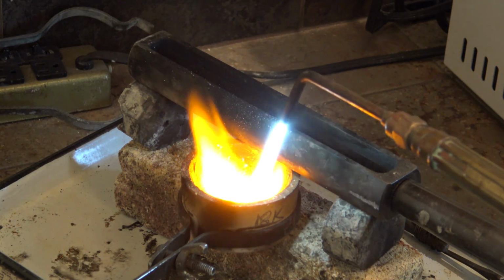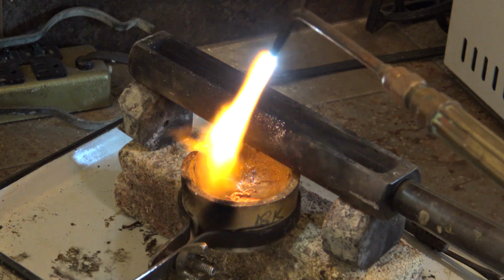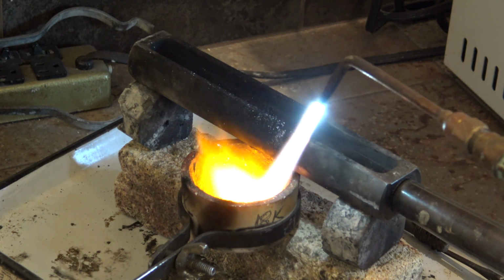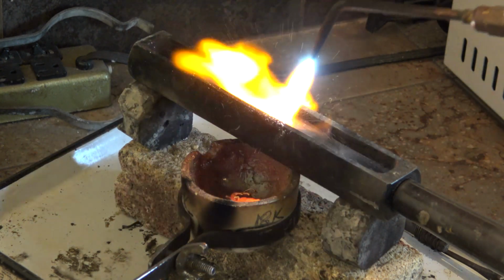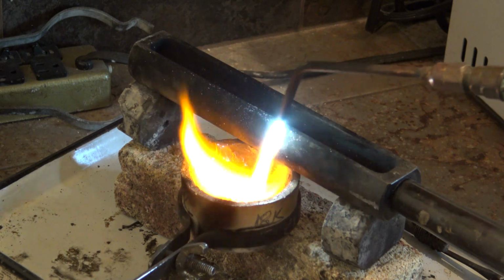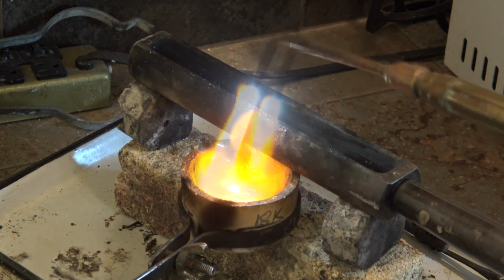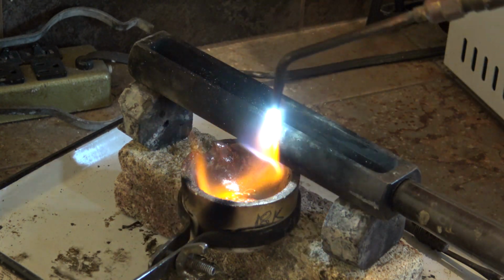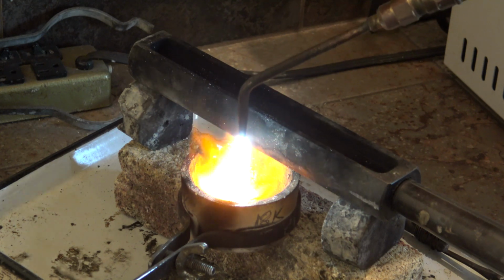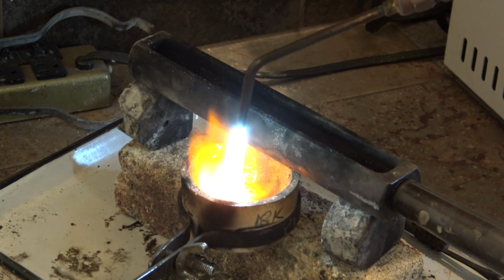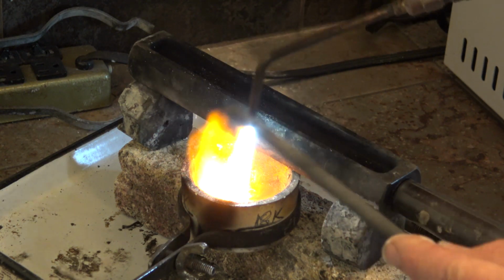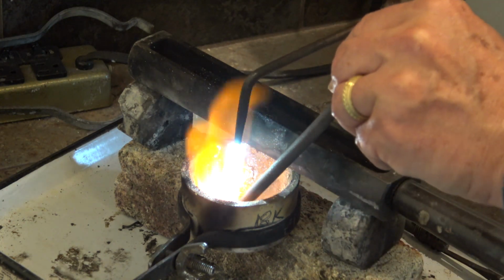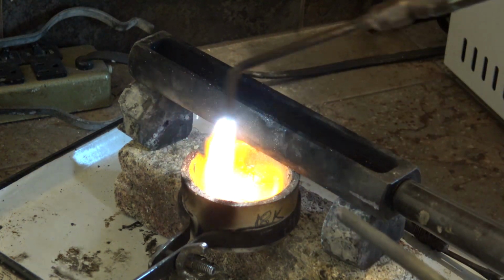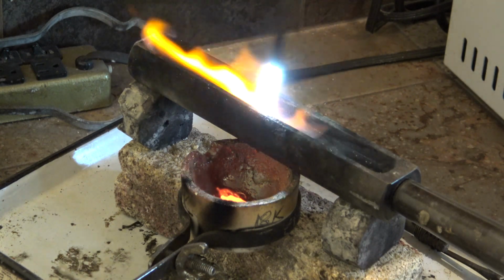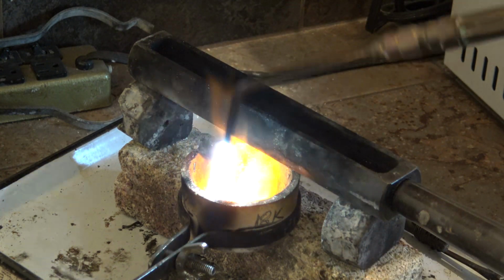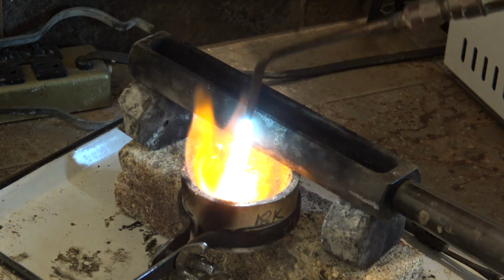So what I do is I add borax flux continuously during my melting process. I will just sprinkle a little bit here and there, and I'm always observing the surface of the metal to see if there's any anomalies happening, and if so, I just will put a little bit of flux on it, which requires removing the flame and then dropping the flux in. I'm also using a carbon stirring rod to remove extra flux and to stir the metal.